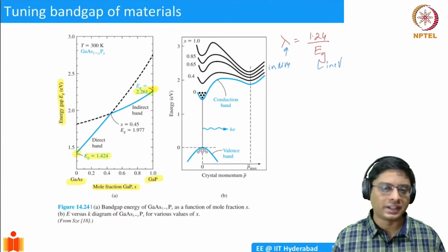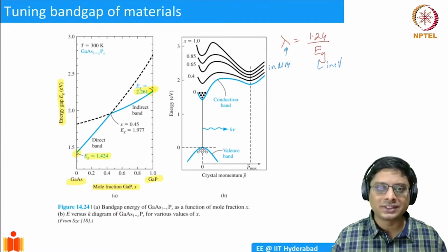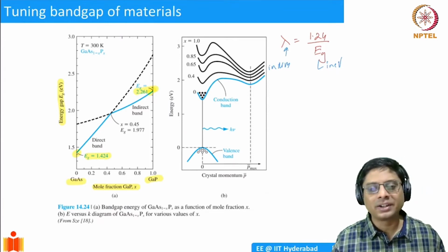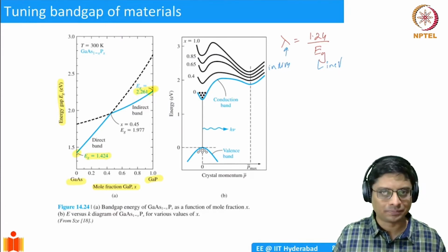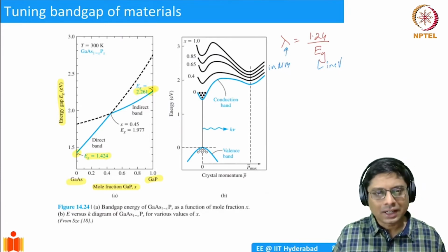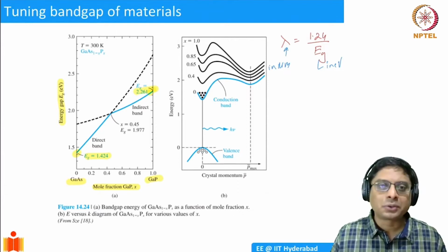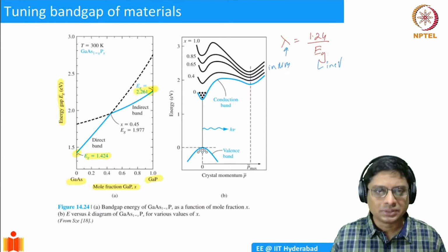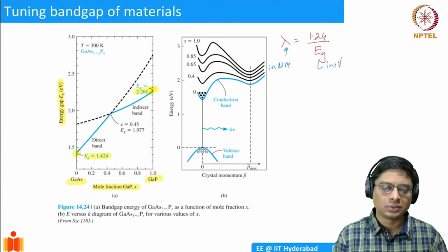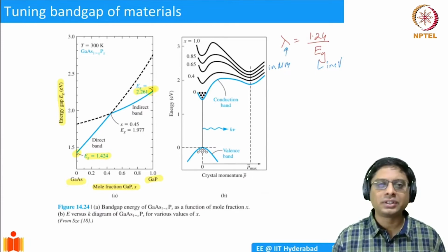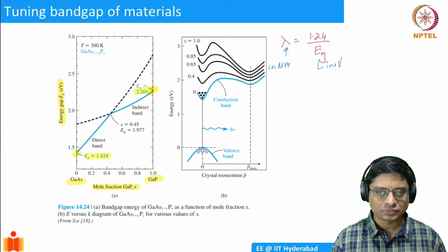It turns out that there is a way, and the approach is to mix the semiconductors. How do we mix the semiconductors? I can replace an arsenic atom with a phosphorus atom. If I do that, I'll increase the band gap slightly. But of course, it never happens that you replace just one atom; you replace a significant quantity. For example, the atomic density of GaAs was 5 × 10^22.